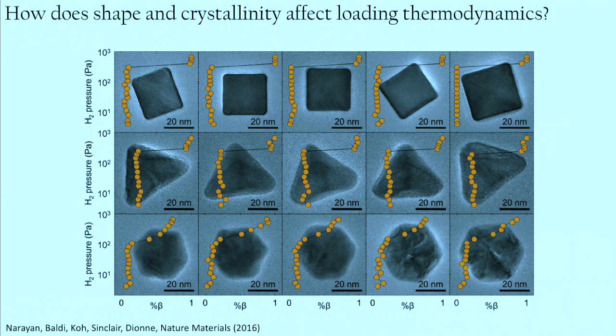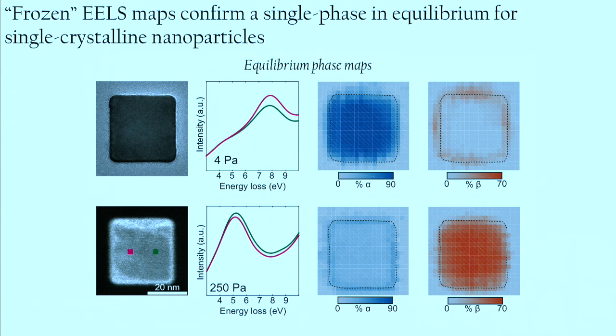And you can see that the thermodynamic properties are quite distinct. So the single crystalline nanoparticles at the top exhibit very sharp phase transitions from the alpha phase to the beta phase, whereas the polycrystalline nanomaterials, namely the icosahedra, have this more gradual transition from the alpha phase to the beta phase. So to figure out what's going on, we developed techniques to essentially flash freeze the sample.